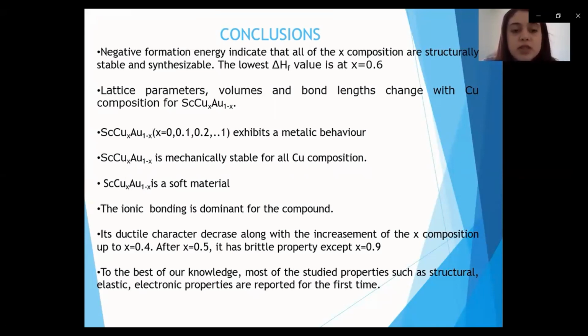Scandium copper gold is a soft material. The ionic bonding is dominant for the compound. Its ductile character decreases with the increase of the X composition up to X equals 0.4. After X equals 0.5, it has brittle property except X equals 0.9. To the best of our knowledge, most of the studied properties such as structural, elastic, and electronic properties are reported for the first time.